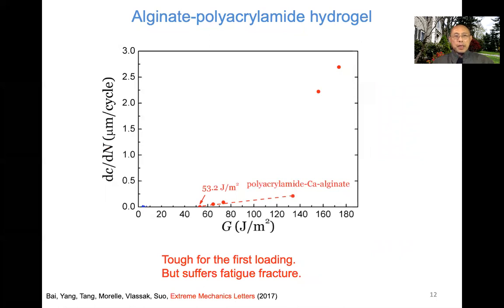We further measure this fatigue threshold. We cut a crack into the sample and measure dC/dN as a function of cyclic load. Indeed, the threshold is about 50 joules per meter squared. Remember, this material's toughness is about 10,000, way up here. So this material is unfortunate. It's tough for the first loading, but it suffers fatigue fracture.